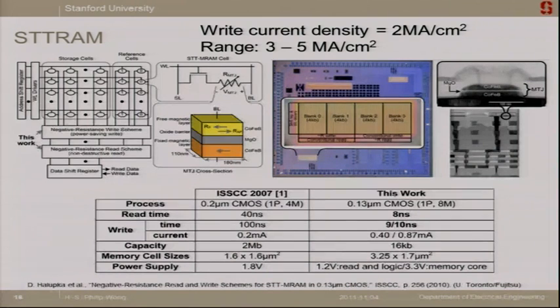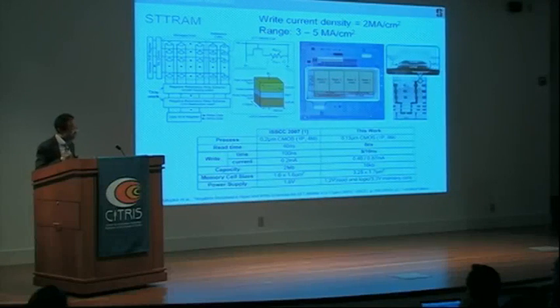If you go through the literature, the write current density is about 3 to 5 megaamps per centimeter squared for the spin torque transfer memory. So spin torque transfer memory also works by current density, so it scales with the device area. As you scale down, it's the same density, but you require a smaller current.